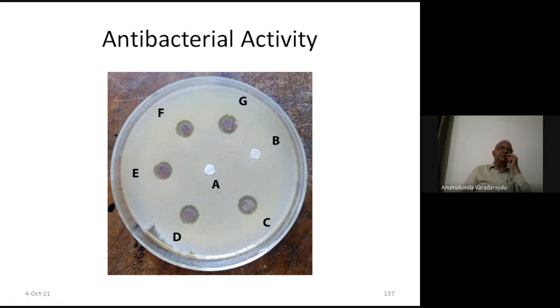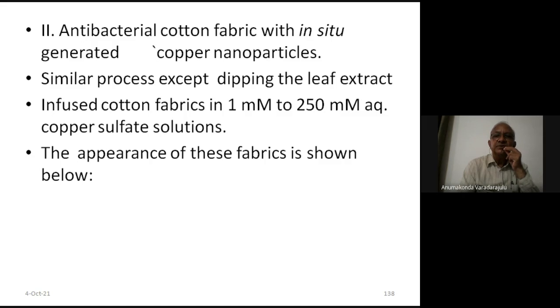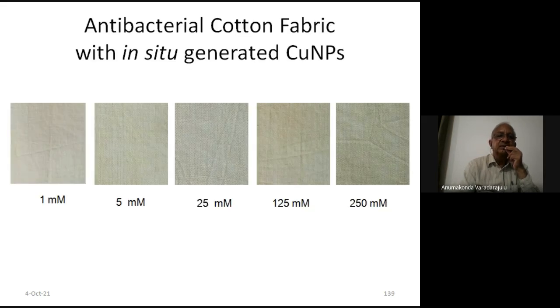But silver is expensive, so then we generated copper nanoparticles inside the cotton fabric. Here we used 1 millimole to 250 millimole copper sulfate solution as a source. So cloth and the solutions, only these two we used. Similar procedure, instead of the silver nitrate solution earlier, we dipped the cotton fabric in copper sulfate solution of different concentrations at 80 degrees Celsius. There is a slight color change, because copper sulfate itself has a pale blue color. So the color change is there, but not as much as in the case of the silver nitrate nanocomposite fabric.